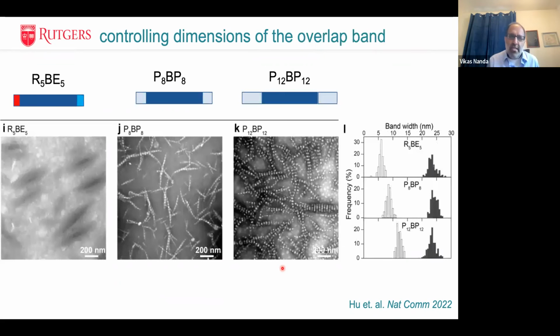So similarly, we can leave the functional domain the same, but now we can change the adhesive domains. So for example, here, instead of using these long proline regions, we now use a charged region, kind of like we saw in that peptide study. We have a basic domain in the beginning, an acidic domain at the end, and now you would expect them to attract each other kind of like magnets and assemble in a staggered fashion. And we can see here we get these banded structures again.